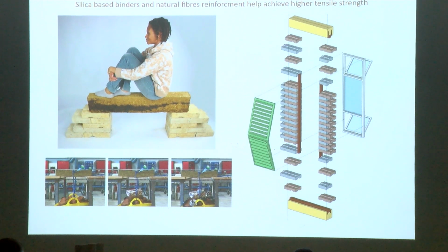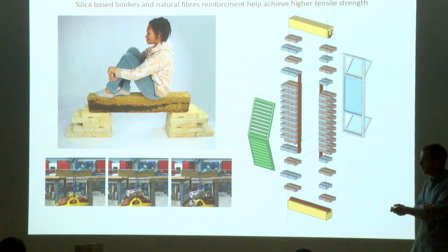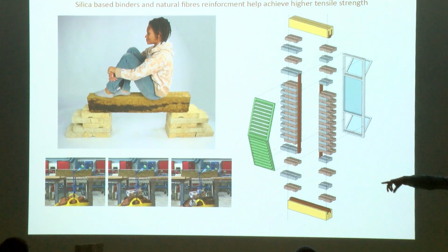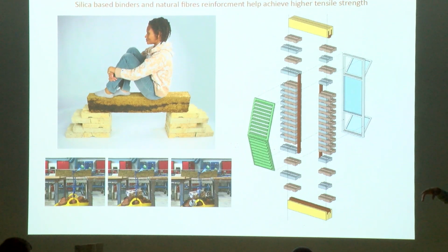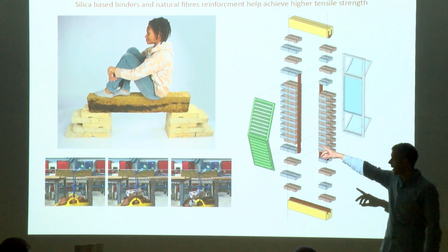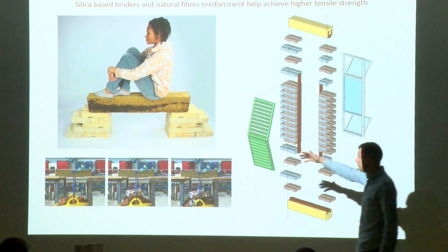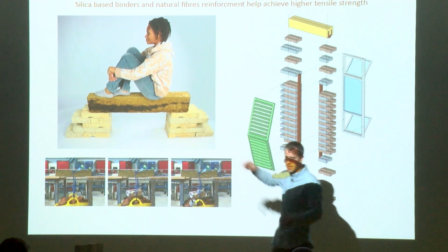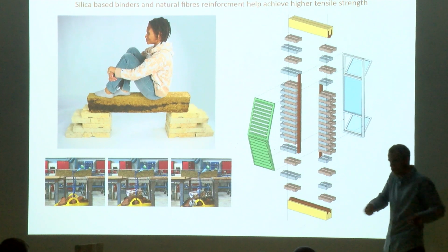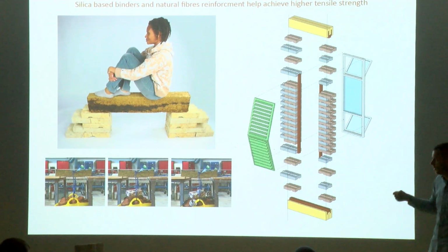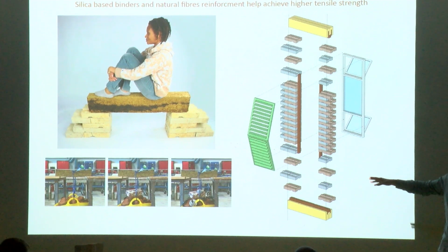We also designed a set of lintels using different binders that allow for tensile strength. So these blocks are good at compression strength, you can pile them on top of each other, but they are quite weak in tension. So we thought that we needed to design a different mix, a different ratio just for the lintels, and we designed that prototype that you see there, where it's only, again, sugarcane bagasse and silica binders, but it has a hessian mesh, which is a natural mesh on the underside, and that mesh improves the amount of load that you can put by almost 10%.